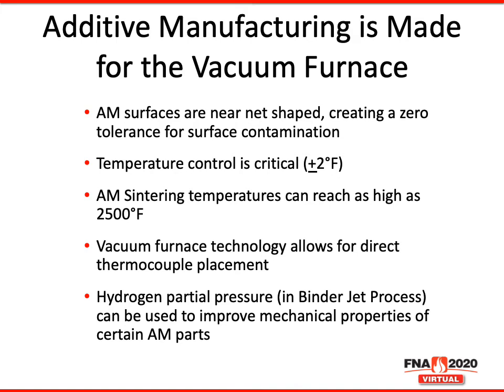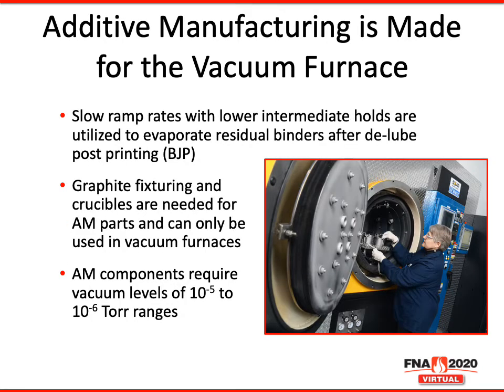So, additive manufacturing is made for the vacuum furnace as well. Additive manufacturing surfaces are near net shape, creating zero tolerance for surface contamination. As stated before, temperature control is very critical, plus or minus 2 degrees Fahrenheit in many instances. Additive manufacturing sintering temperatures can reach as high as 2,500 degrees Fahrenheit. Vacuum furnace technology allows for direct thermocouple placement. Also, hydrogen partial pressure in the binder jet process can be used to improve mechanical properties of certain additive manufacturing parts.